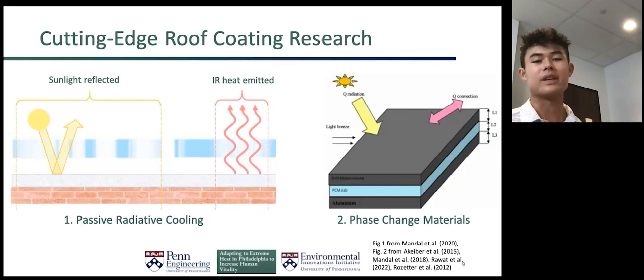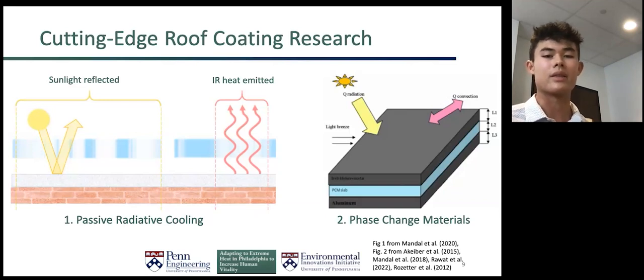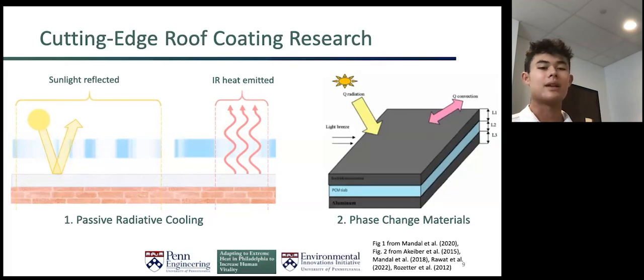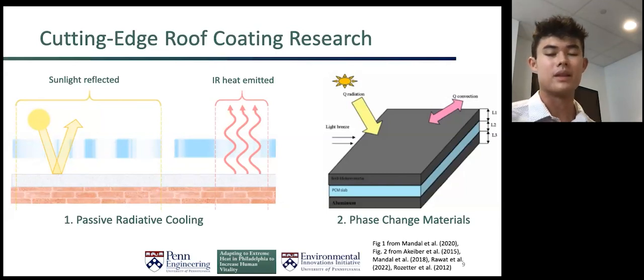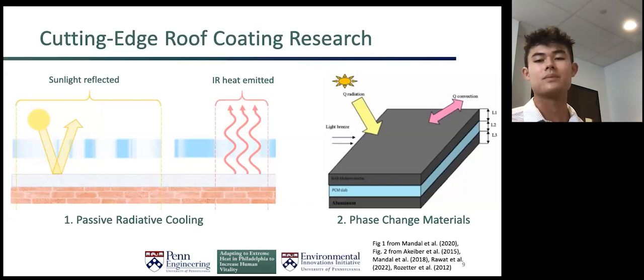And researchers are seeking to further optimize the amount of light that can be reflected, and then also the amount of longer wavelength IR heat emitted through the infrared atmospheric window. And the first approaches to this used reflective pigments like titanium dioxide. And more recently, a subclass of porous materials have emerged that substitute microscopic air voids for those pigments that have a similar light scattering effect without having any physical pigment present. And these have achieved really impressive results recently.